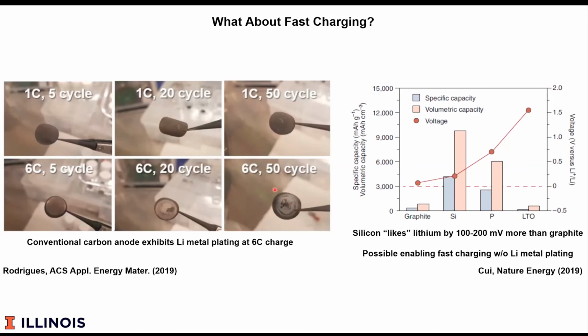So what's happening here? Well, graphite only likes lithium by a very small number of millivolts. And so what happens is that you try to push the lithium into graphite, there's simply not much driving force. So another alternative is to go, so here's graphite, it sits at a few tens of millivolts. The other is to go to these titanates. The titanates love lithium. And so you can fast charge this quickly, but because the voltage is so high, you're going to lose 1.5 volts of your cell and the energy drops down.